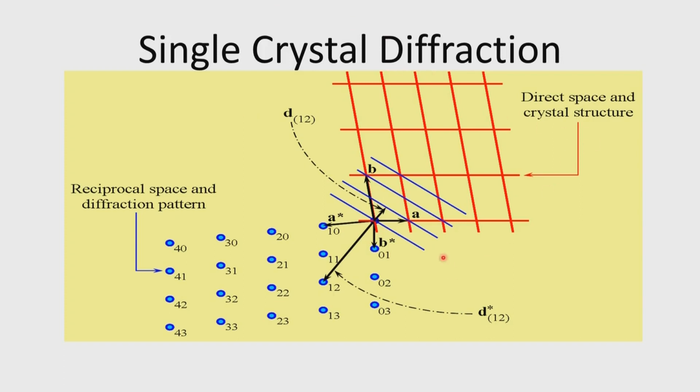It is essentially the way in which the reciprocal space develops, with a value which is proportional to 1 divided by the distance. So, in other words, it generates the reciprocal lattice point. Planes in the direct space will generate points in the reciprocal space, and therefore we call them the reciprocal lattice points, and each and every reciprocal point therefore corresponds to a plane in the crystal.